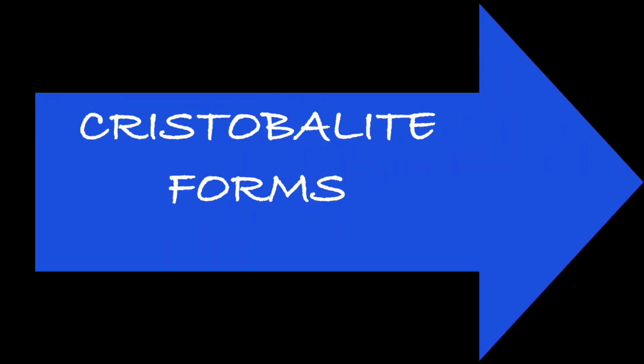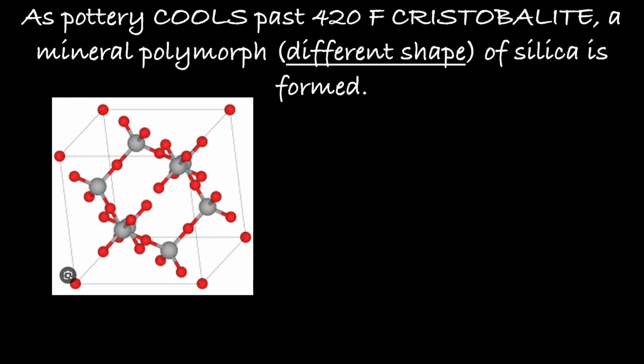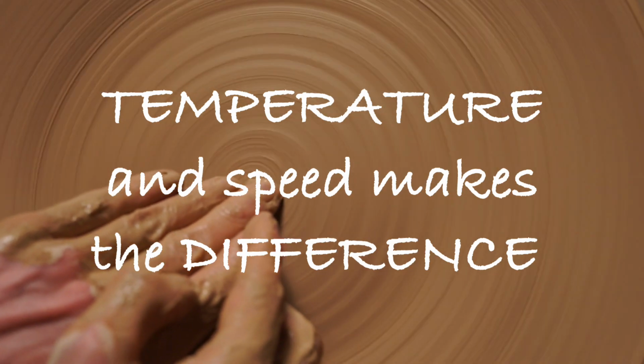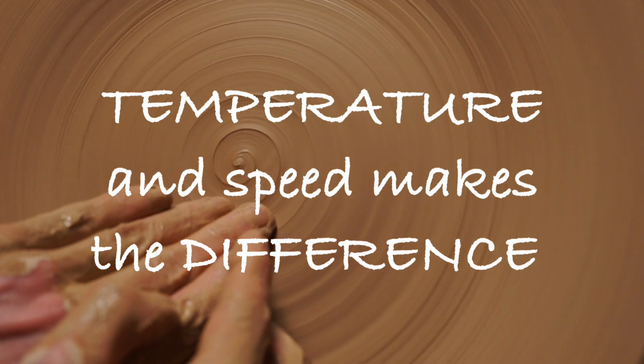Finally, something called cristobalite forms. This is something that occurs as the clay cools. As the piece cools past 420 degrees, a mineral polymorph, which is basically just a different shape of silica, is formed. Slow cooling around 420 degrees is critical so that cracks don't occur as the molecules rearrange and settle. Temperature and speed make all the difference. So there you have it. It's a pretty amazing process.